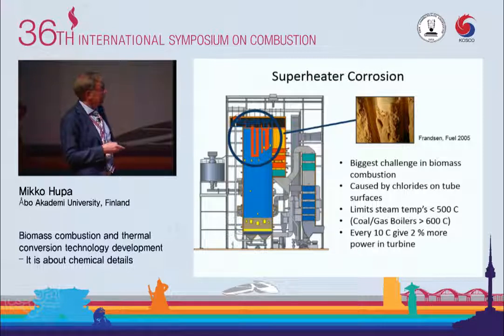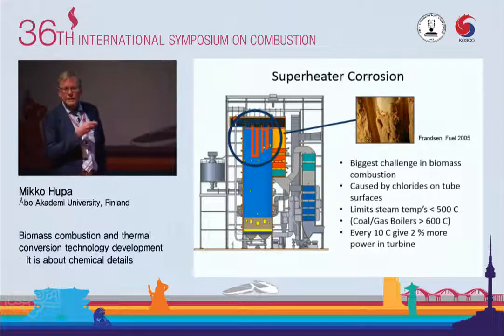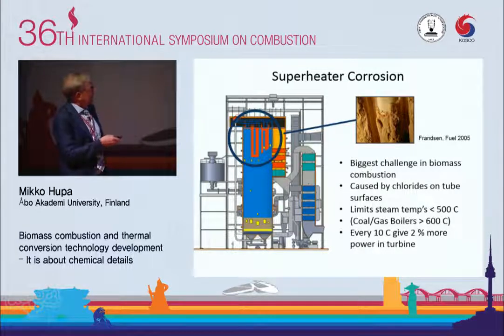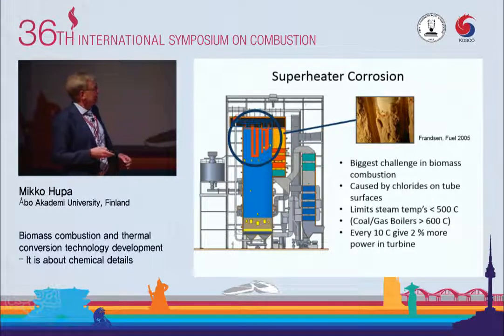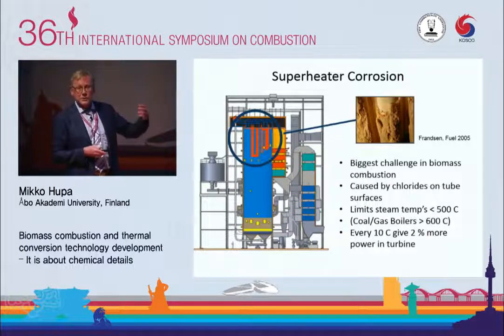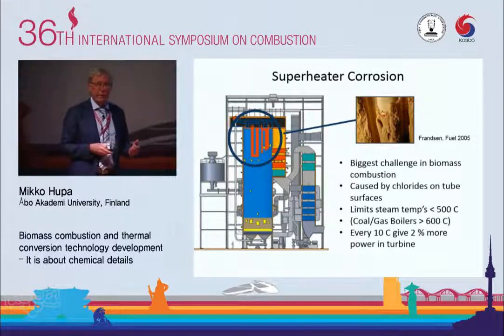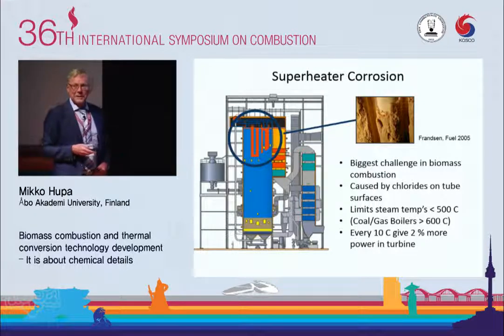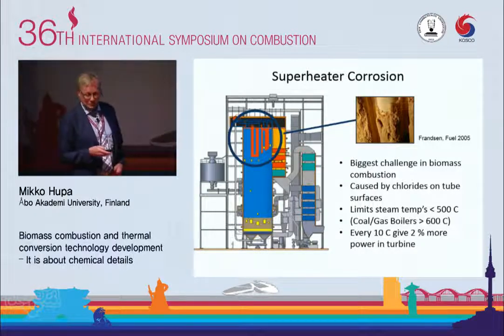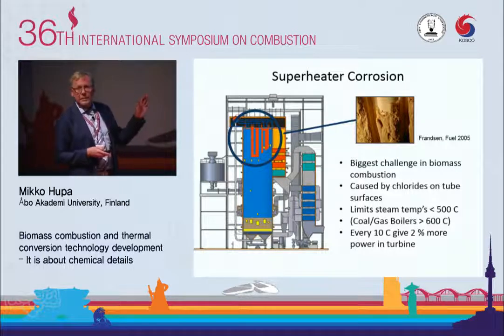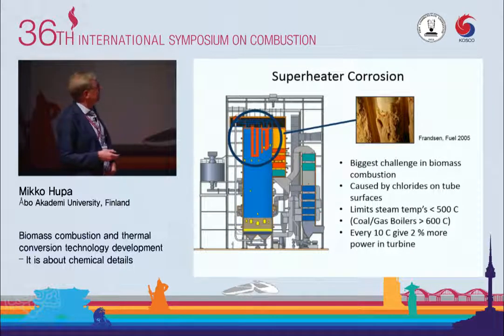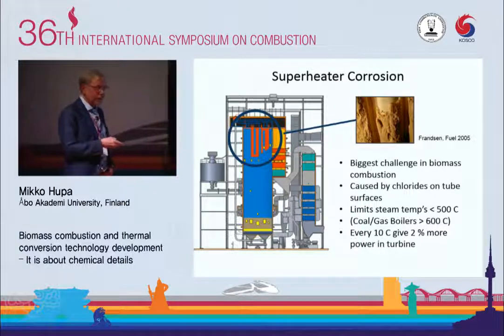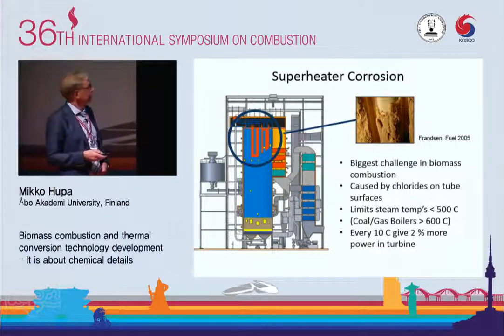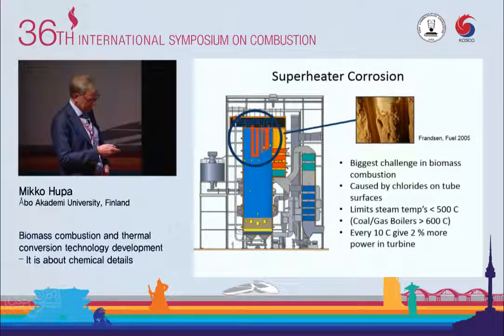While, as you know, in coal boilers we can go beyond 600, and the materials issue is still not there. And a simple rule of thumb is that every 10 degrees we dare to heat superheater steam higher gives 2% more power in the turbine. You can check if that is a correct rule of thumb, but in that range, which means that there is a big interest in improving this situation. And our boiler manufacturing colleagues, with whom we work together, are extremely concerned about finding solutions to improve the efficiency, the power production efficiency.